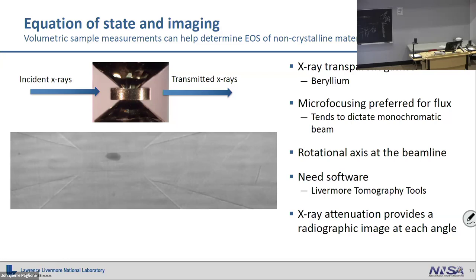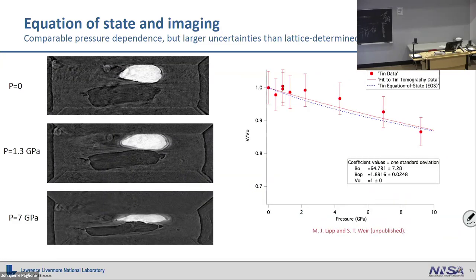You need some software to do that. We have a particular set of software that we use, but there are several different types of tools on the market that come especially with tomographic setups you buy for the lab. Basically you're measuring the attenuation as a function of pixel and reconstructing that into a volume. Here's an example of what it looks like at zero. There's a pressure marker underneath it. And as we go up to 7 GPa, you can physically see that the volume of this thing is shrinking as we put pressure on it.